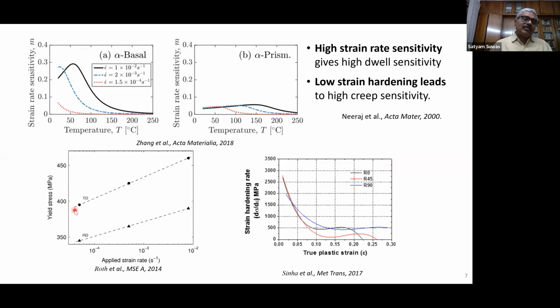There is a reason behind it, because if we just see here is the yield stress versus applied strain rate response of a titanium material, which is generally basal textured in hot roll condition. Basal texture is substantially different along rolling and transverse directions. And this happens at almost all the strain rates. So therefore, it was observed that the dwell fatigue response is sensitive to texture of the material, right?